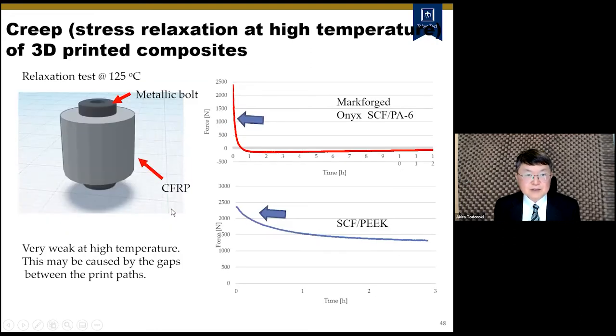And this slide showed the effect of temperatures. We conducted relaxation tests at 125 degrees Celsius, and Markforged polyamide 6, short fiber polyamide 6, Onyx, within a very short time, the force becomes almost zero. So this cannot be used in high temperature applications.